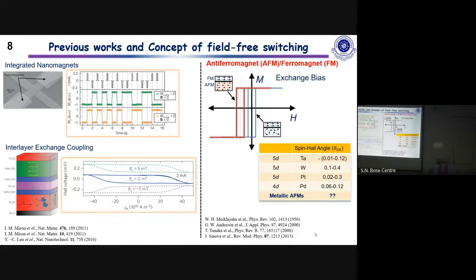So we tried to have a much simpler alternative, and the thing that we thought of was to use an antiferromagnet bilayer system. So we were actually the first group who showed this. Our idea was that we know that an antiferro-ferro bilayer system has an inbuilt magnetic field at the interface arising from the exchange bias, which we already know. But at that time we didn't know whether the antiferromagnet itself could also be a source of spin-Hall effect. So the idea is, if this antiferromagnet is a source of an exchange bias field and is also a source of spin-Hall effect, then using the same system, you can serve the dual purpose. It could be a source of spin-Hall and it could also be a source of magnetic field, and then you can, in principle, have field-free switching with this bilayer kind of system. So that was the idea.